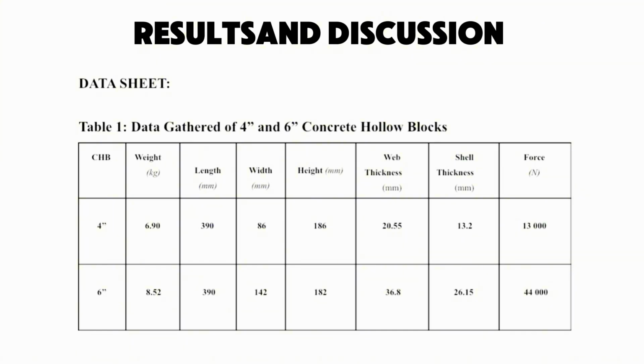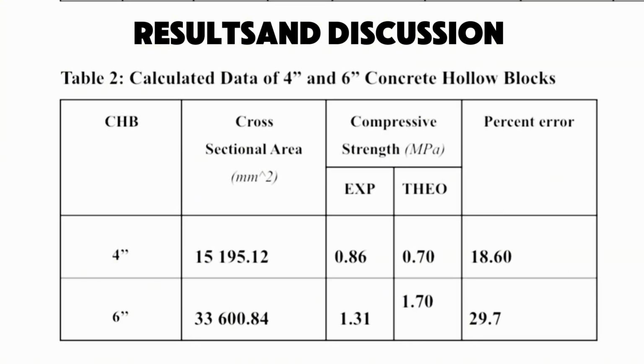The web thickness of the 6 inches CHB is 36.8 mm, which meets the ASTM C90-23 requirement of a minimum thickness of 19 mm. But its shell thickness of 26.15 mm is more than the ASTM C90-23 requirement of 25 mm. According to ASTM C129-23, both the web and shell thickness of the 6 inches CHB meet the minimum requirement of 13 mm. Table 2 indicates that the 6-inch CHB obtained a compressive strength of 1.31 megapascal, which is higher than the 0.86 megapascal compressive strength that was obtained by the 4-inch CHB.